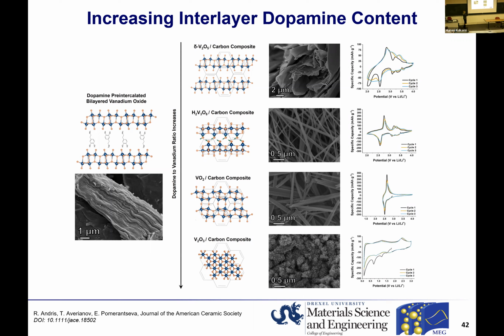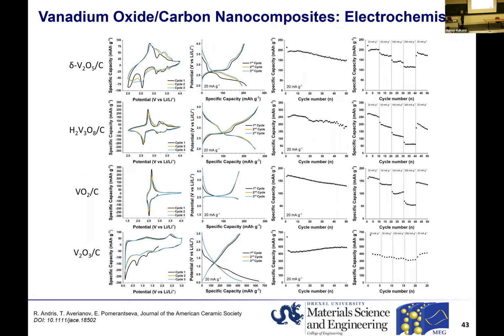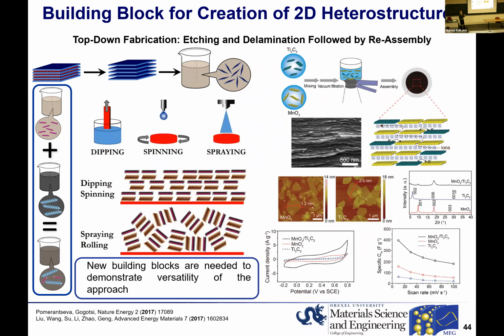And instead of our favorable V2O5 phase, we now make vanadium dioxide and even vanadium oxide with vanadium in the oxidation state of 3. While all these materials showed fine performance and could be studied further, this is beyond our interest. So we just decided to leave it at that, publish this result, showing that dopamine reduces transition metal ions during the synthesis. We wanted to utilize an alternative approach to make this heterointerface. The bottom-up approach didn't work, so we decided to switch to a top-down approach.